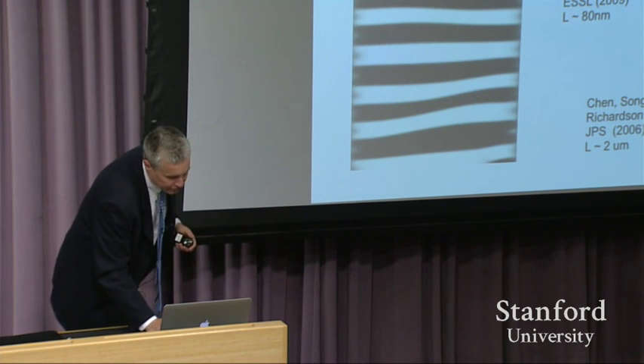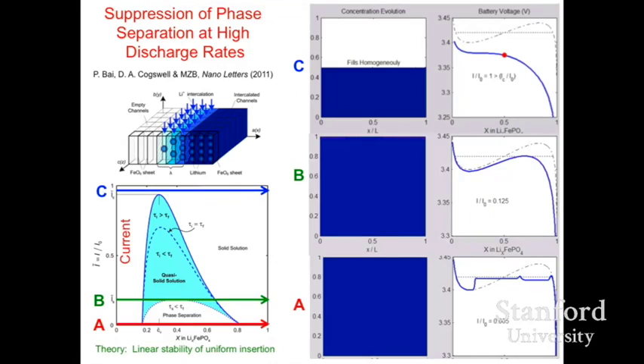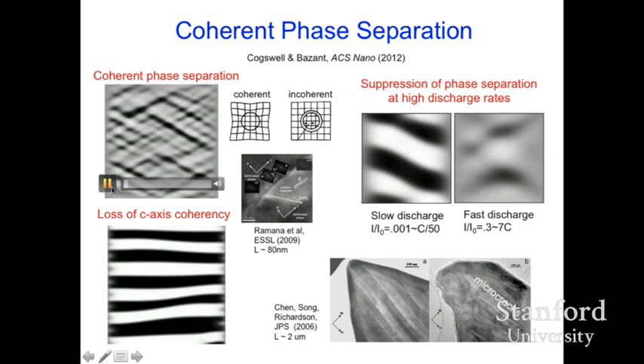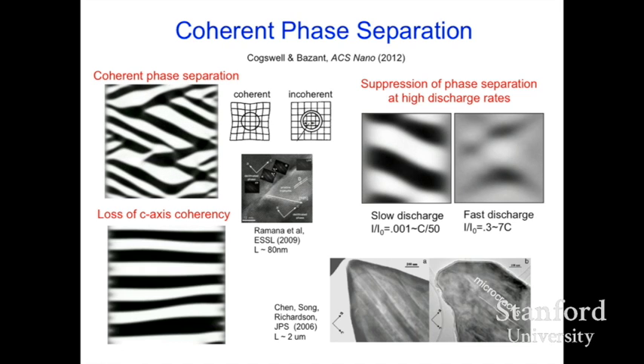And so as I showed you before, if I go back to this slide, imagine I went to 50%, it's homogeneous, and then I let it go. You're going to see it drop down into the phase separation region, but now we'll see it happen with elastic coherency strain. And there you see the instability. It forms these stripes, which want to be at a certain angle.